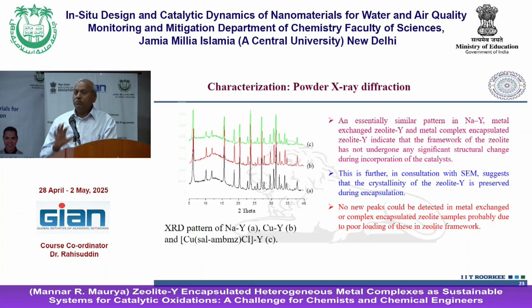After encapsulation of the metal complex, crystallinity is maintained. You will see that there is no change in peaks, 1, 2, 3. I do not see any. Now, the question comes: what about the metal complex? Do you get any peak due to the metal ion? Very rarely, tiny peaks sometimes. If you have a considerably good amount of metal complex encapsulated in a certain number of voids, then you should be able to see it, otherwise you won't be able to see that.